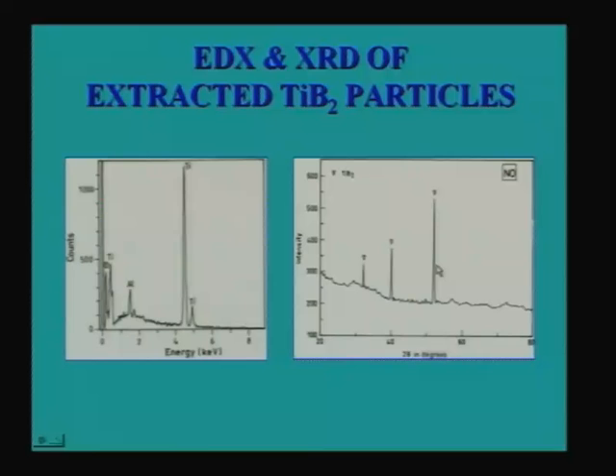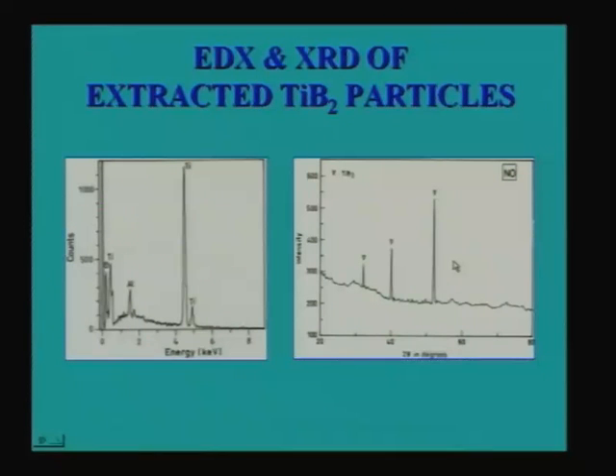If you take these powder particles, which have come from the extraction of TiB2 from the aluminum TiB2 composite, where you dissolve all the aluminum and collect whatever residue is left, and subject that residue to XRD, what you see is this kind of peaks which are completely TiB2 peaks. This confirms that no Al3Ti is forming, because that is one of the problems that I told you in the last class: whenever you are making a TiB2 composite with aluminum matrix, there is always a chance for Al3Ti also to form. So one has to really control it.